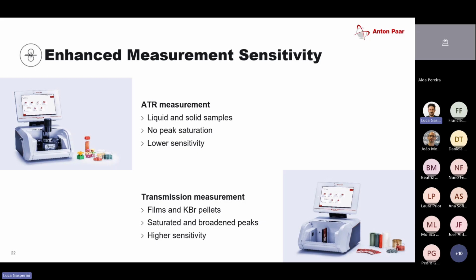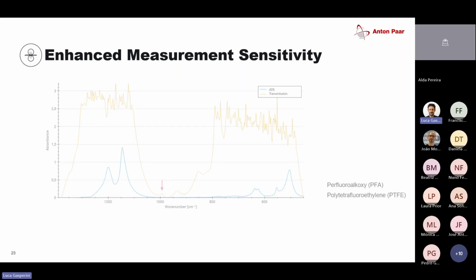The problem is, everyone who has prepared a KBr pellet, and I did this once, knows this is a horrible task. Half of the time it breaks, and then you have to do it all over again, and also you have to make sure that it's very homogeneous. So typically, if you want a very fast and easy measurement, you go with ATR measurement.